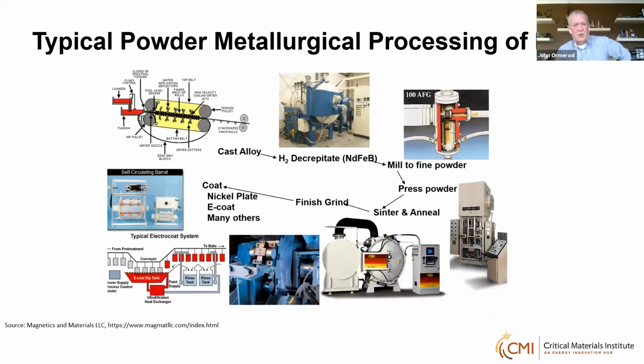Now, what I want to show here is actually a much more detailed process that is typical for a neodymium iron boron magnet. In this case, with neodymium iron boron, we start with the melting and casting through a strip casting process, where the cooling rates are much higher than is typical for, let's say, an ingot casting. Here we're talking about cooling rates in the 10 to the 4 degrees per second range. That alloy is then crushed to a coarse particle size through a process called hydrogen decrepitation, milled in a jet mill, pressed and aligned, sintered, heat treated, finished ground. And then in the case of neodymium iron boron, because of their poor corrosion resistance, those magnets are almost always coated in either a metallic or a polymeric coating to provide the necessary corrosion resistance.